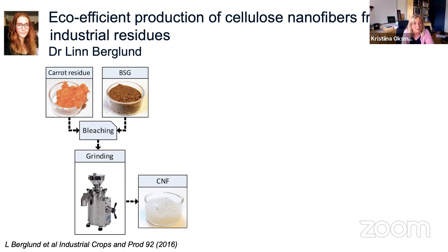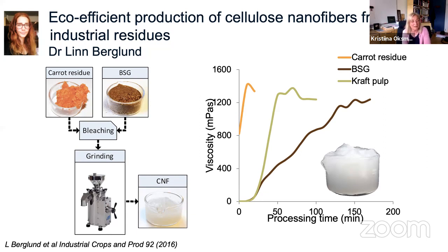And usually we are doing pre-treatment and bleaching, for example, removing lignin, which is holding these nanofibers, gluing them together. So we need to remove that polymer. So bleaching is done, and then we are doing grinding, and that grinding is mechanical separation. And we are doing that grinding until we have a specific type of gel, these cellulose nanofibers. And during that process, we are measuring viscosity and of course time.